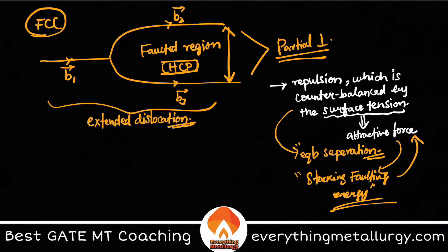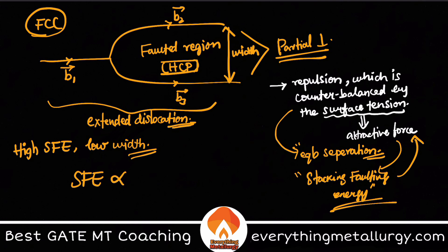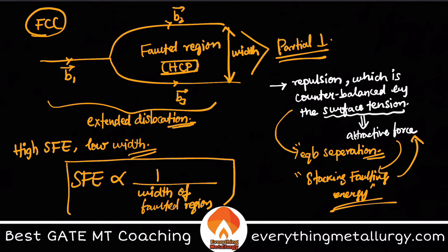Stacking fault energy can be seen as an attractive force between the partial dislocations. If I have high stacking fault energy, the attractive force is more dominant, so the equilibrium separation is less — meaning the width of the faulted region is low. Conversely, low SFE gives high width. To conclude: SFE is inversely proportional to the width of the faulted region.